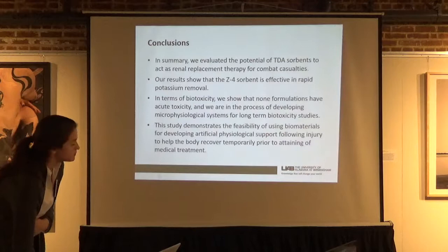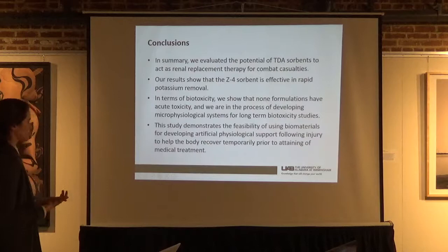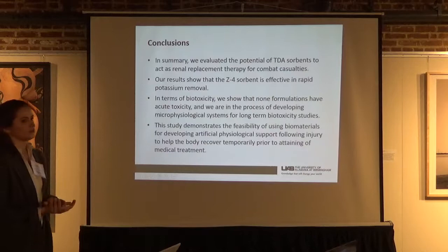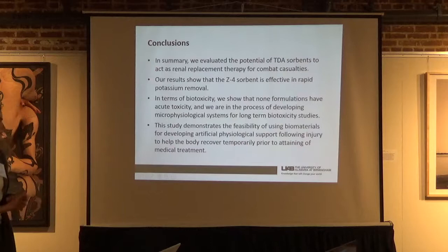As a conclusion, in summary, we evaluated potential sorbents that act as a renal replacement therapy for combat casualties. Our results show that the Z4 sorbent is effective in rapid potassium removal. In terms of toxicity, we showed that none of the formulations have acute toxicity, and we're in the process of developing MPS systems for long-term biotoxicity studies. Overall, this demonstrates the feasibility of using biomaterials in developing artificial physiological support following injury to help recover temporarily prior to attaining medical treatment.